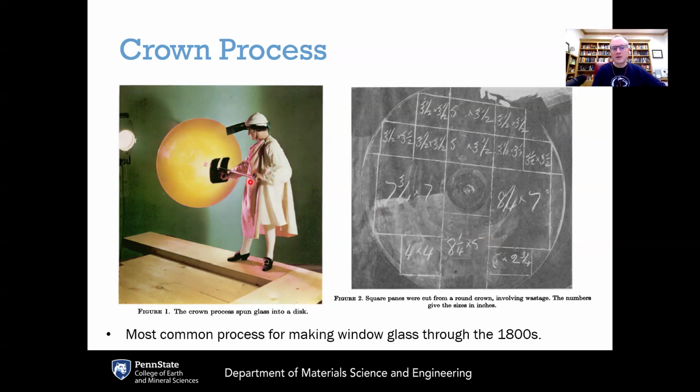The reality is that if you go back to how this glass was made in medieval times, it was made by putting a gob of glass at the end of this rod here, spinning it out, and then the centrifugal force basically pulls it out into a disc. And of course, in the middle, it is naturally thicker compared to the outside part. And then the artisan would cut this up into different pieces that would be used for the stained glass windows.